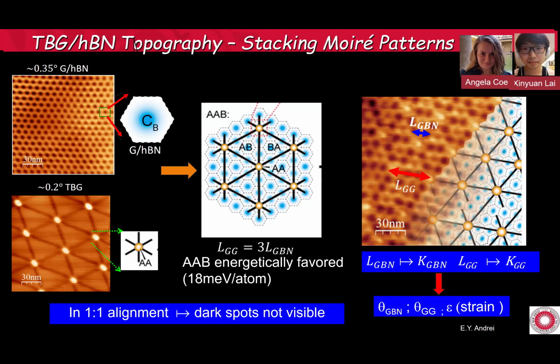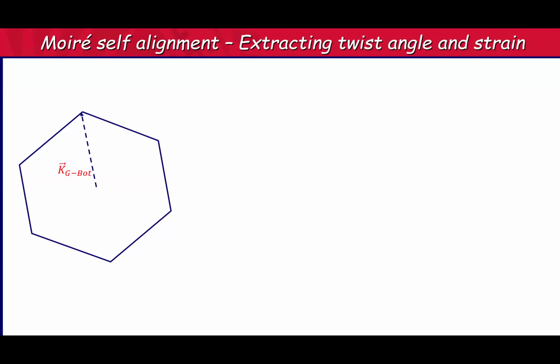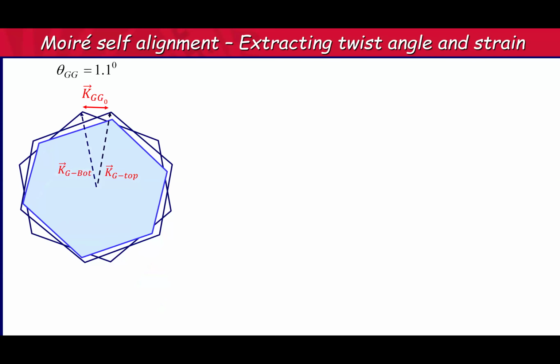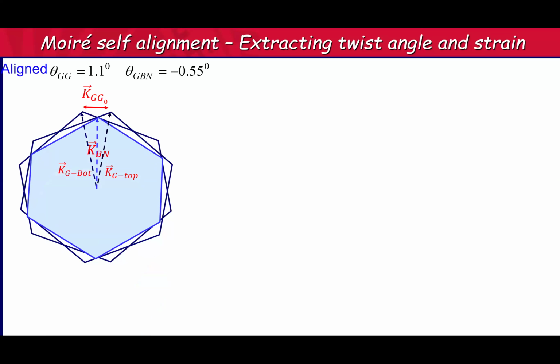One important point here: when you are perfectly aligned, one-to-one alignment, which is where we want to be, you don't see any dark spots. It's only the bright spots that show up. So here, in reciprocal space, this is my first, the bottom graphene layer. This is my second graphene layer, so Kg bottom, Kg top, and this is KGG naught, without any strain. And now I'm bringing in the boron nitride and aligning it at 0.55 degrees, and this is what it looks like.